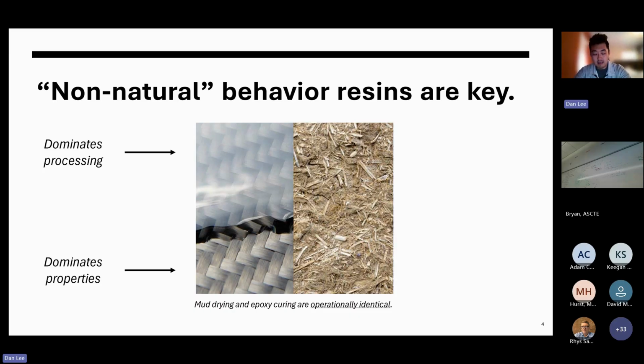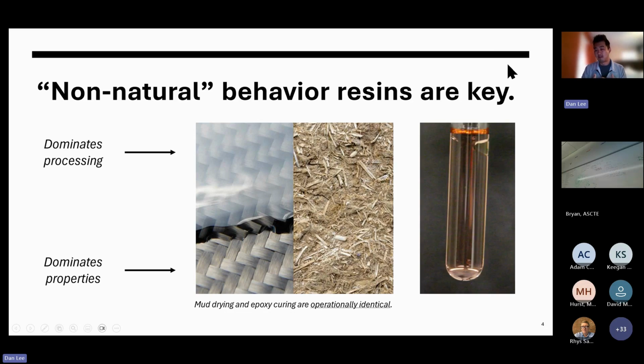So as polymer chemists, we were digging into literature and doing a lot of research on these very odd behaviors. We landed on a phenomenon that today is known as frontal polymerization, and that's been known since the 1900s. It's very difficult to induce for all sorts of technical reasons, but I want to show you what it looks like in general. This is a vial of our resin sitting at maybe 20 Celsius, so ambient temperature. What we do is initiate a curing reaction, and then we can watch it happen in real time.